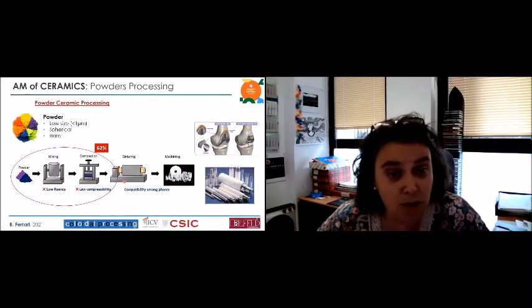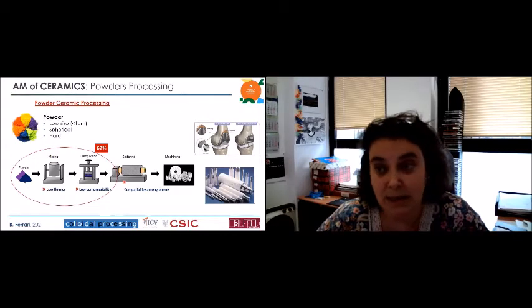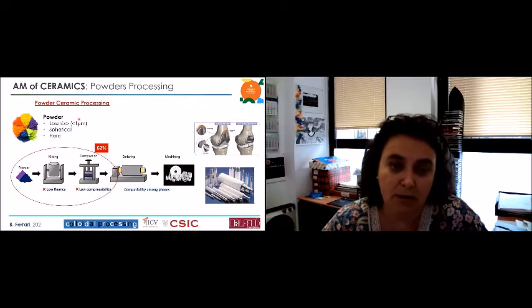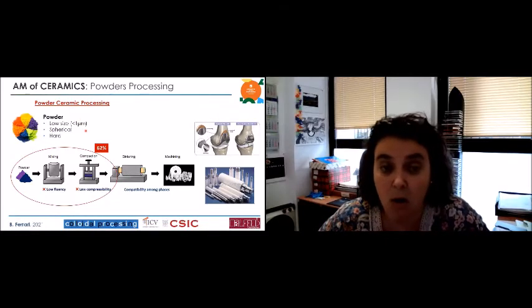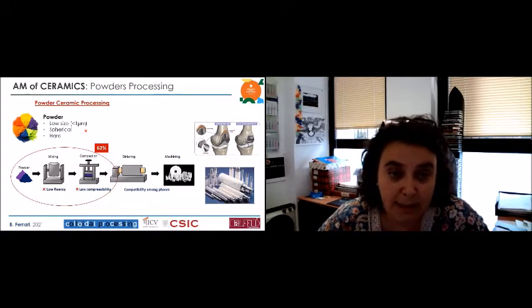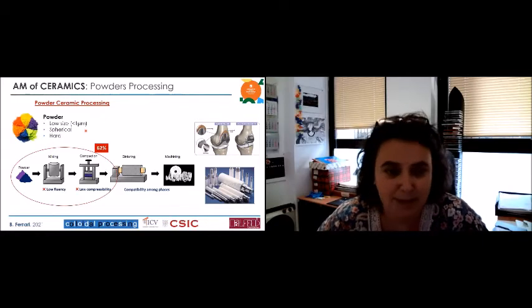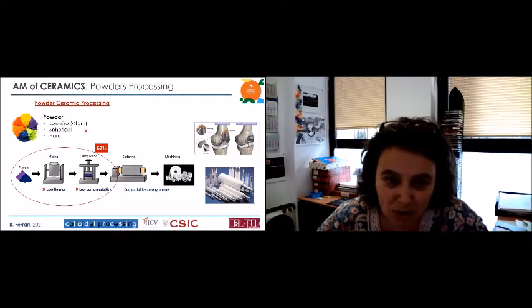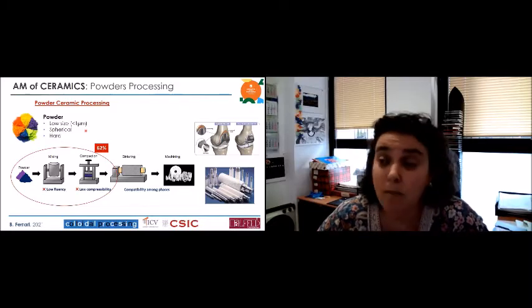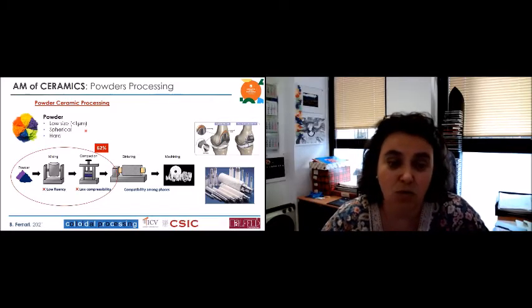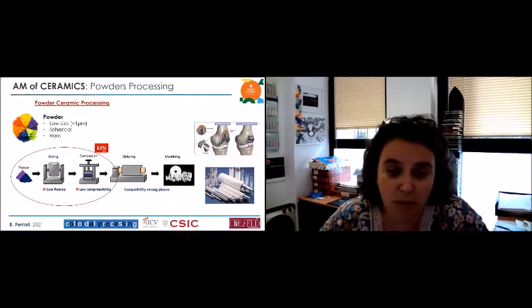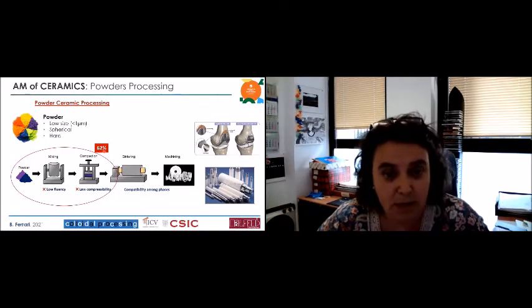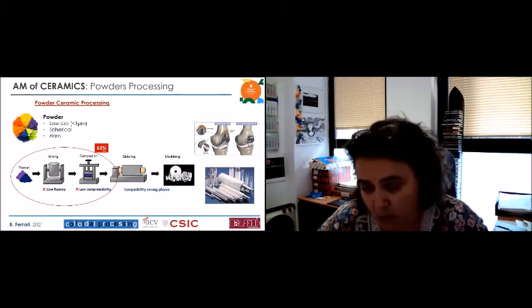Because if you go to ceramic processing, pressing is not exactly the same. Most of the time in technical ceramic, we are working with small particles. That means we are working in the micrometric or submicrometric size. We are working with spherical particles, hopefully. That means when we have huge shape factors of the particles, it is quite complicated for us. And our particle is hard. So when we arrive at the compaction process, we are at 57% of density before sintering, if we are lucky, right?